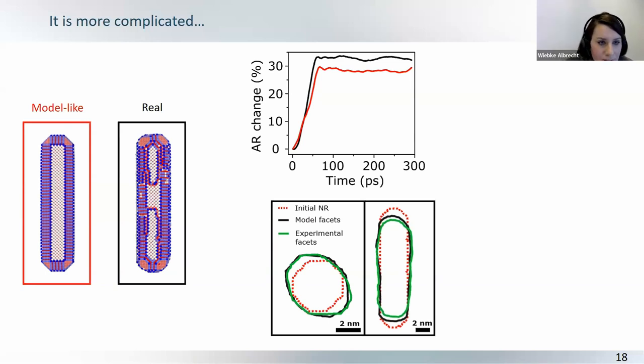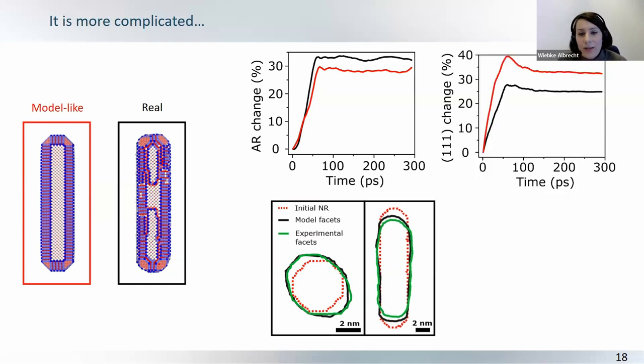It has unfinished surface edges, as you can see here, it has kinks and steps, where atoms can more easily diffuse to, so they do not have to create a completely new atomic layer.